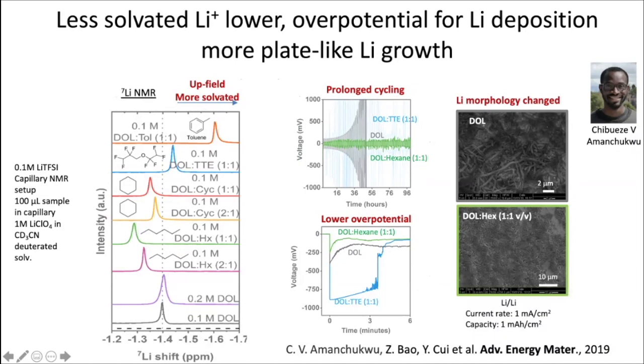So these approaches have shown great promise. We decided to approach this in a systematic way. So here we started by first investigating how we can tune the solvation of lithium and how that impacts the deposition. In this case, we take the DOL ether-based solvent, then we added different non-solvating solvents such as hexane, cyclohexane, and toluene. And then we use lithium NMR to study how these solvents can solvate the lithium.